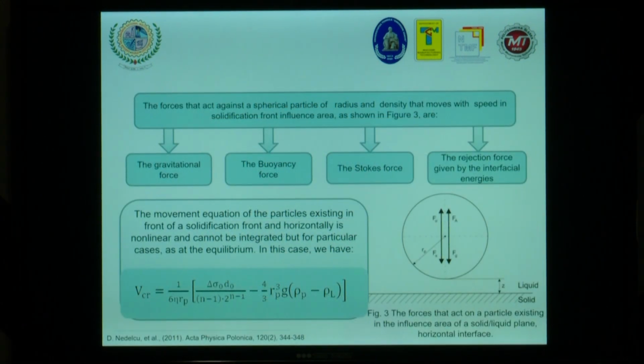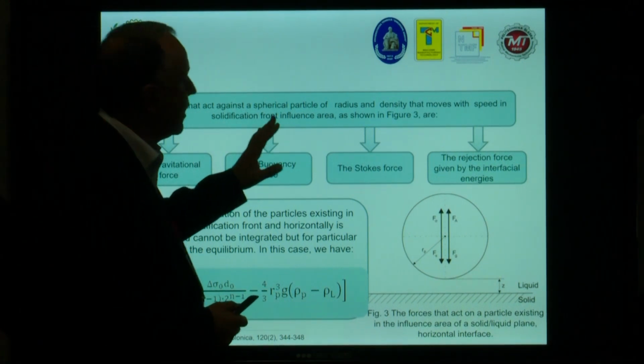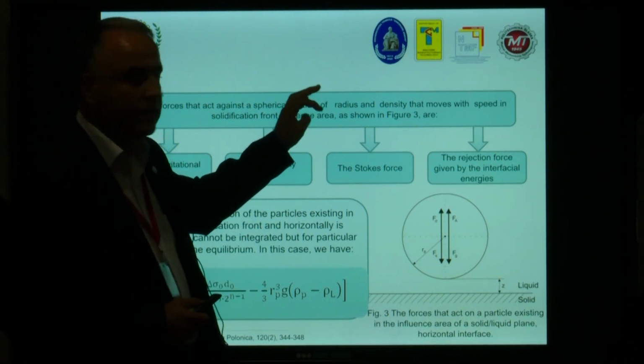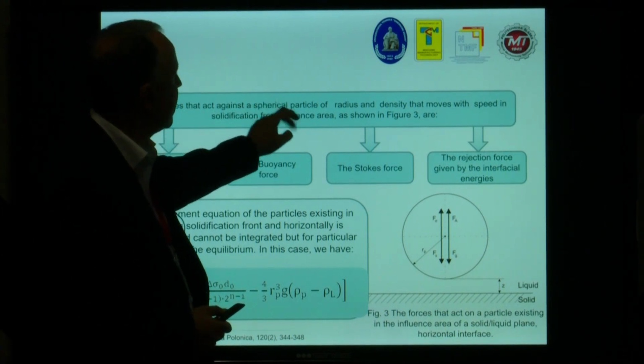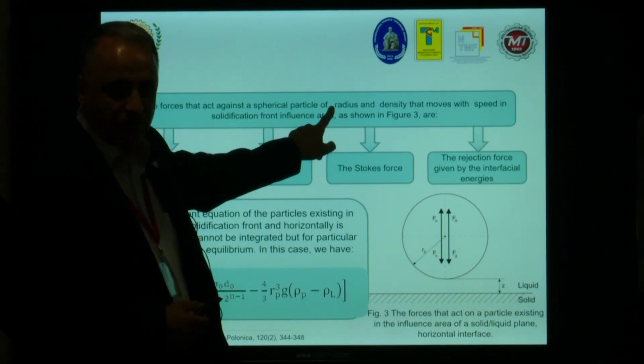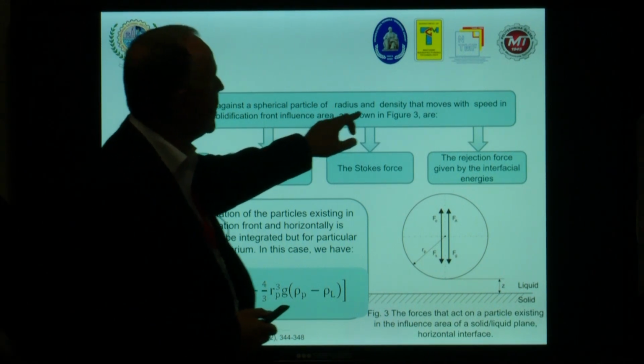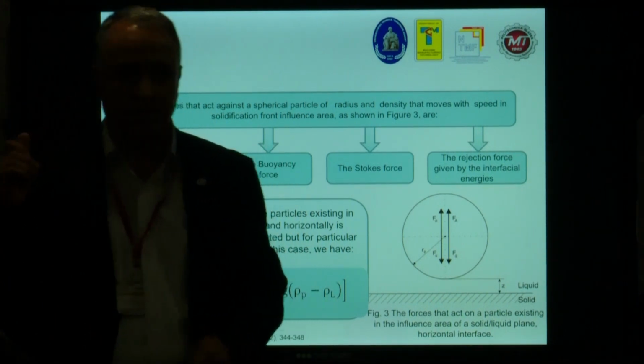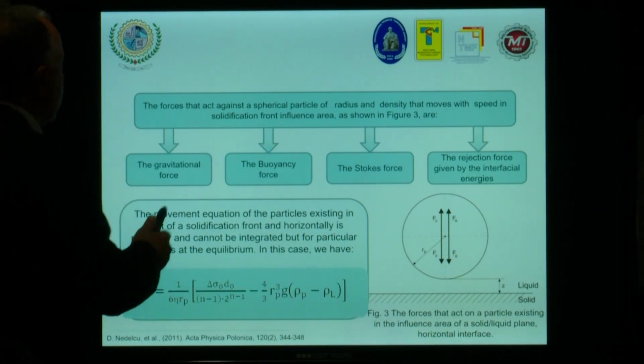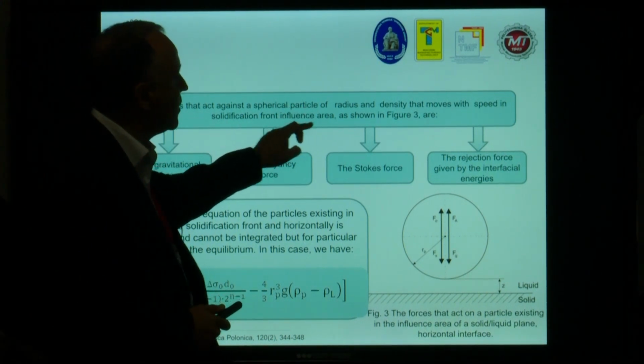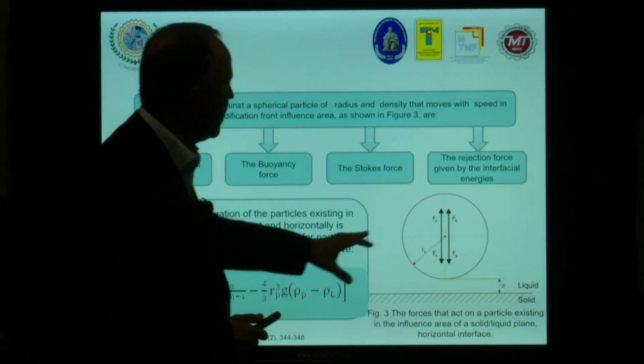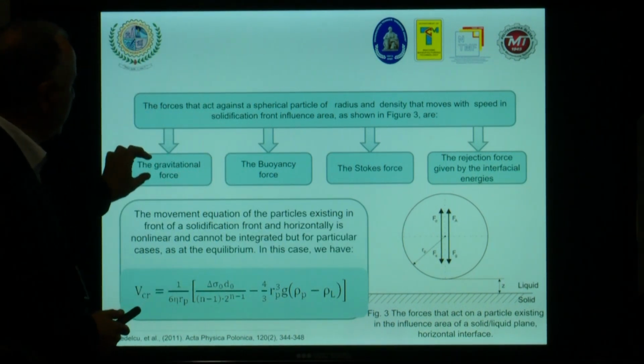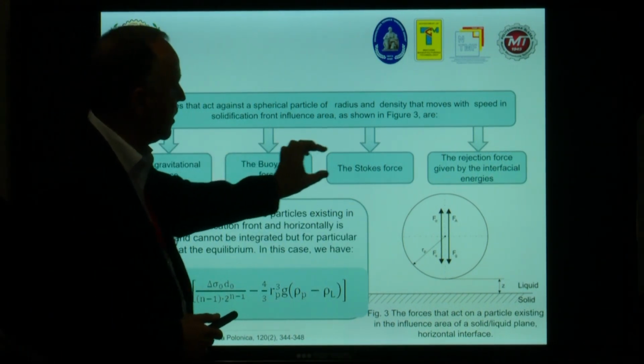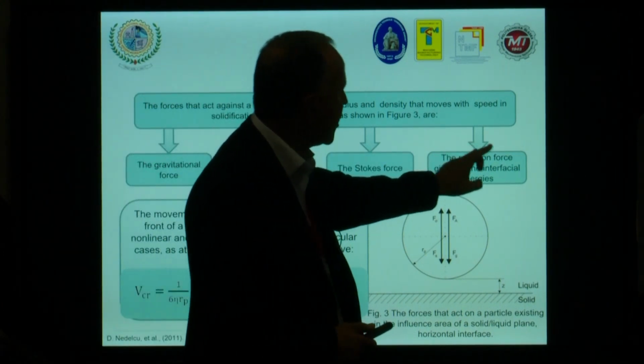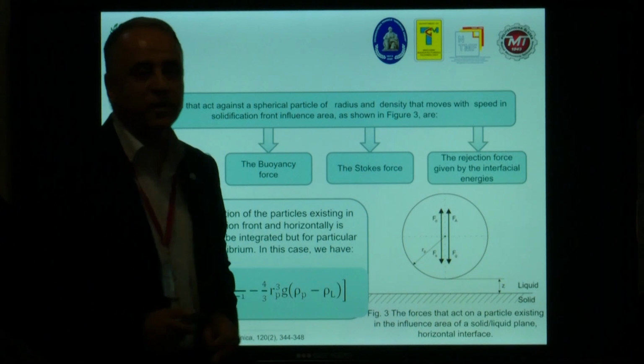You can see the force that acts against a spherical particle, here the radius is missing. So the force that acts against a spherical particle, with radius RP and the density, that moves with the critical speed, VCR, in the solidification front influence area, you can see as shown in figure number 3. So the forces: the gravitational force, the buoyancy force, the Stokes force, and the rejection force given by the interfacial energy.